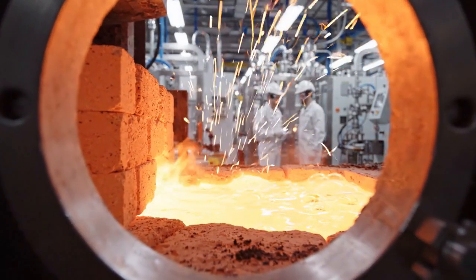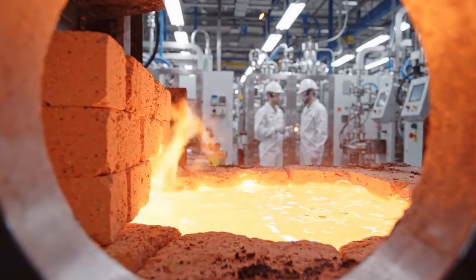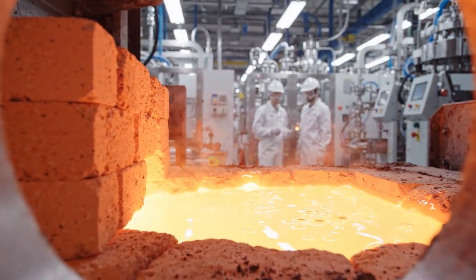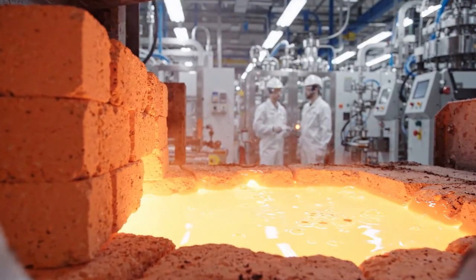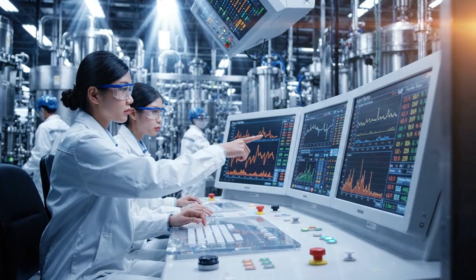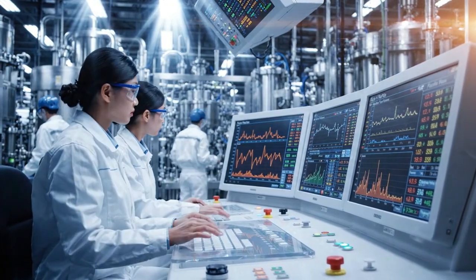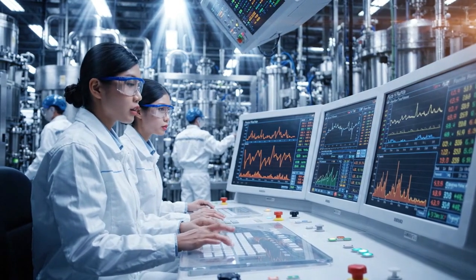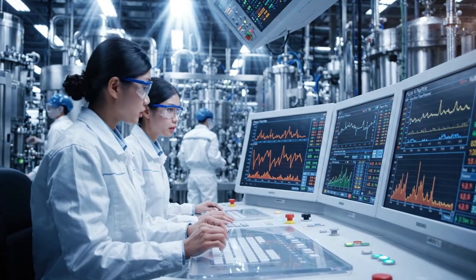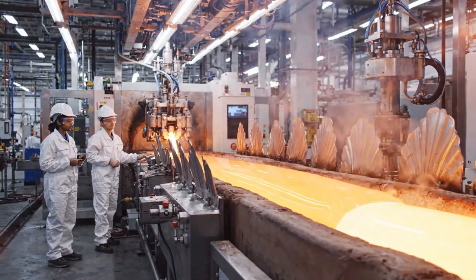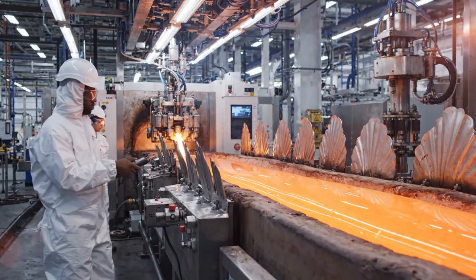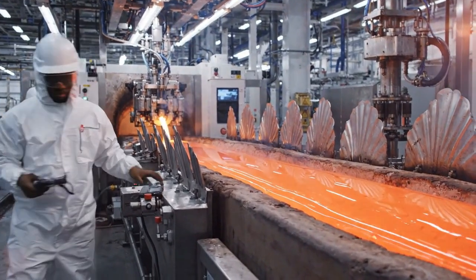Furnace refractories must resist 1500 degrees and the corrosive attack of molten glass for over a decade. Refractory failure would force a catastrophic furnace shutdown. Furnace control balances fuel input, air supply, batch rate, and pull rate to maintain the precise conditions needed for high-quality glass production.